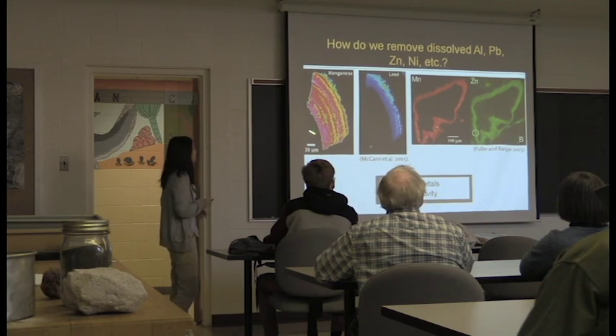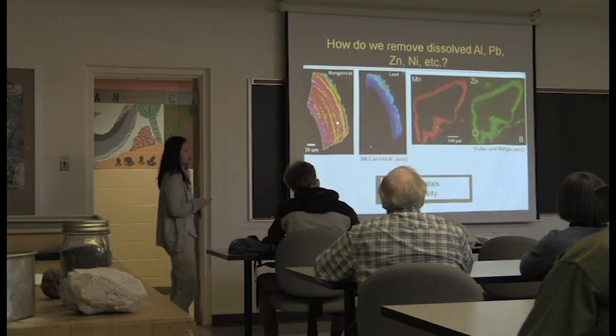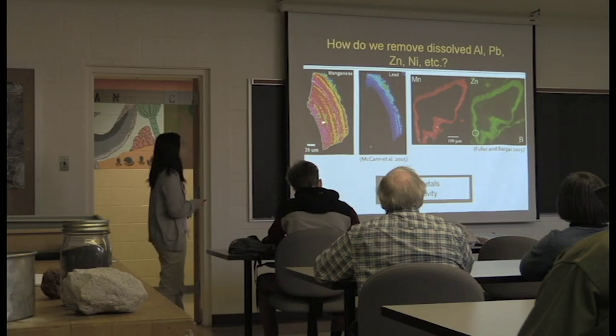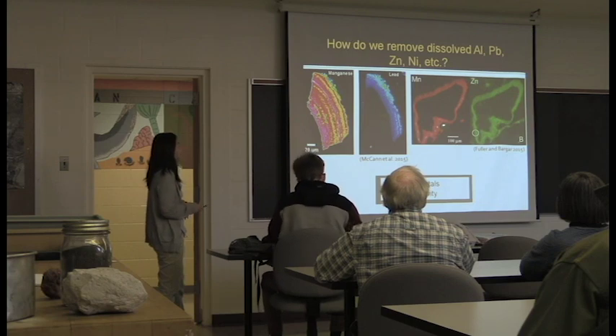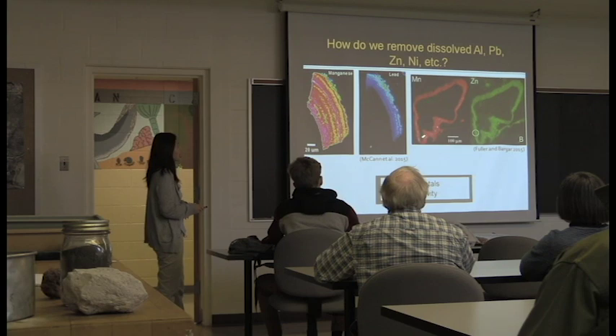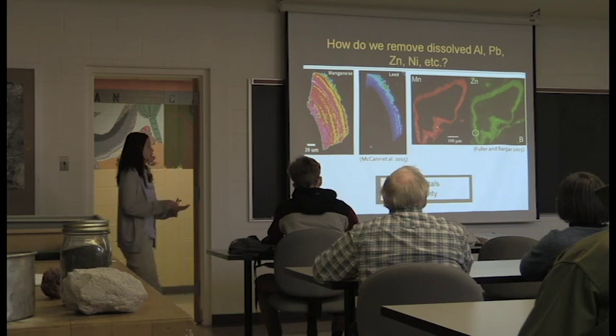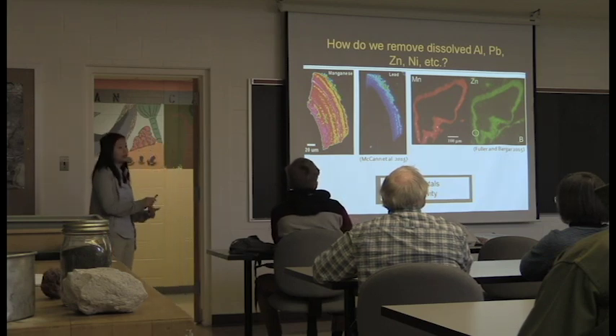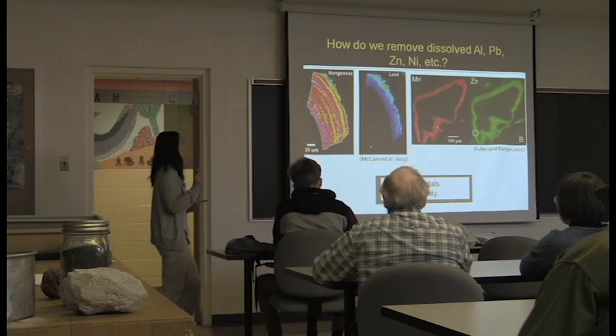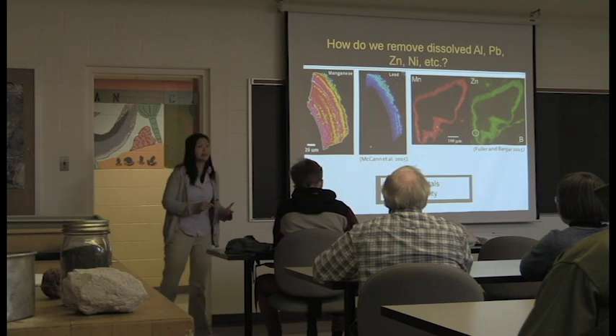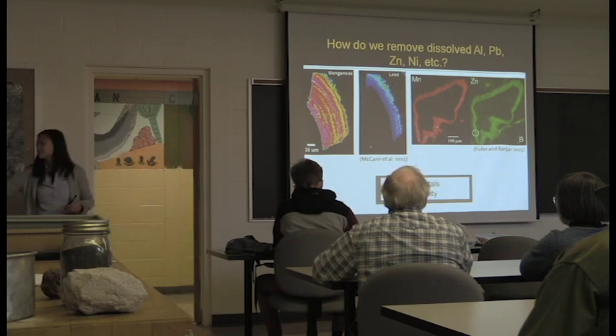This is a chemical map of a natural manganese oxide, and they found that lead is associated with these manganese oxides on the outer rim of this particle. They also find this for zinc. So here is a manganese oxide coating in red, and zinc is attached to all of the manganese oxide associated with this, which tells us that manganese oxides are great because they can attract a lot of these contaminant metals, and they're also very reactive in that sense.